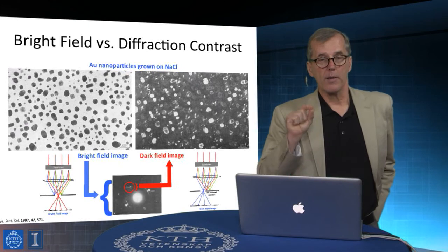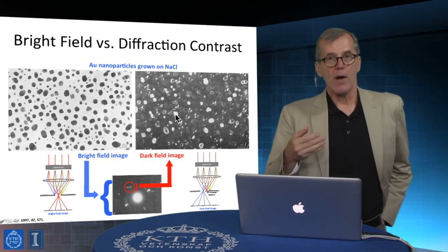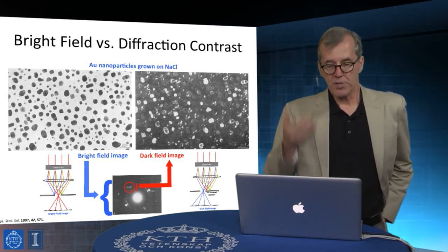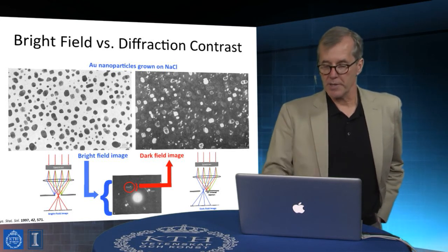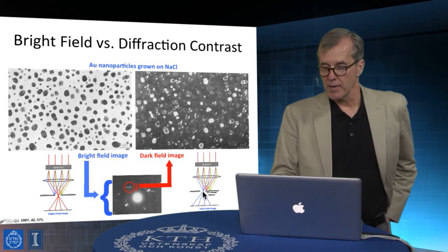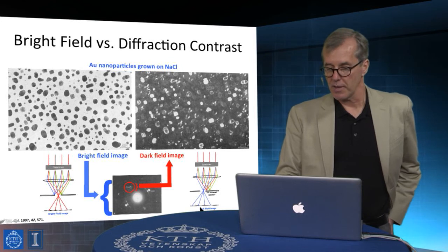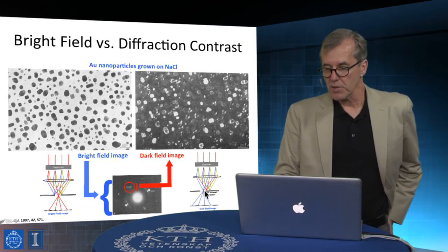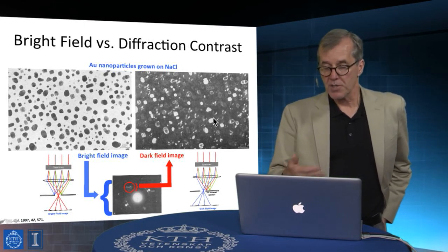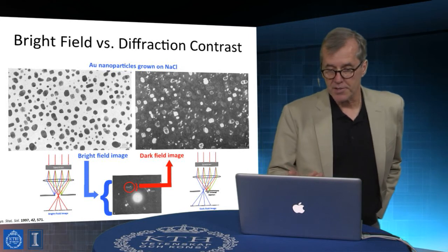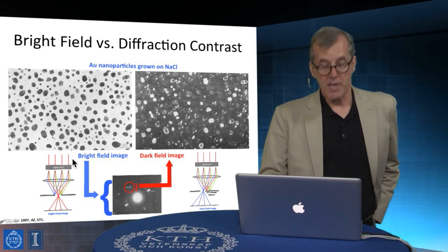The things that appear bright are crystals that project a zone axis that has the correct orientation to scatter electrons to that diffraction point, okay? And that's the image that we get, for only those crystallite habits that correspond to that diffraction condition. And so that is another way of providing contrast in this normal mode of TEM imaging.